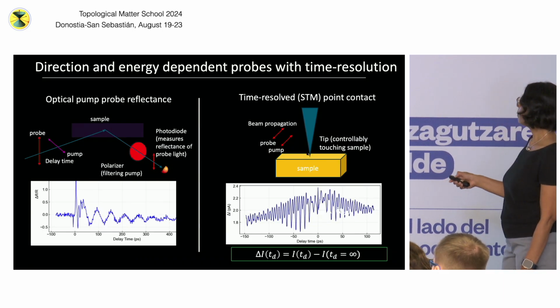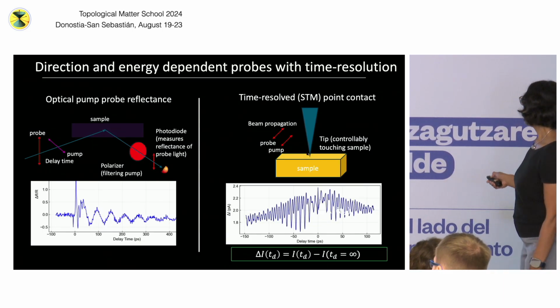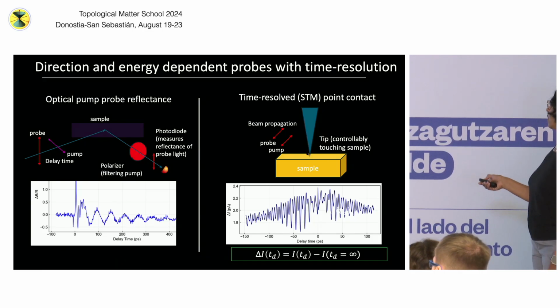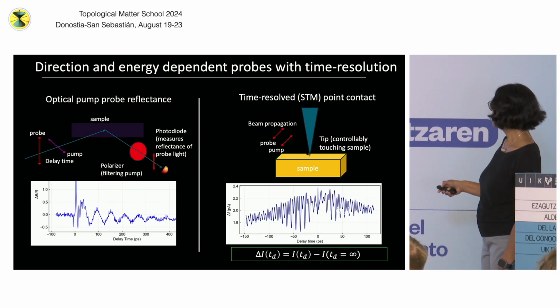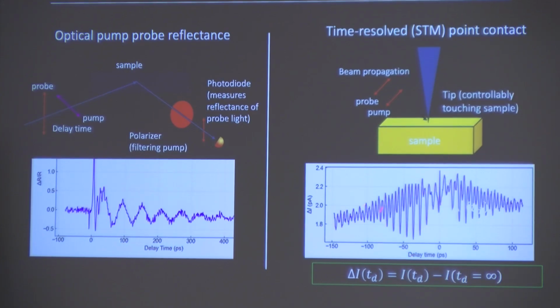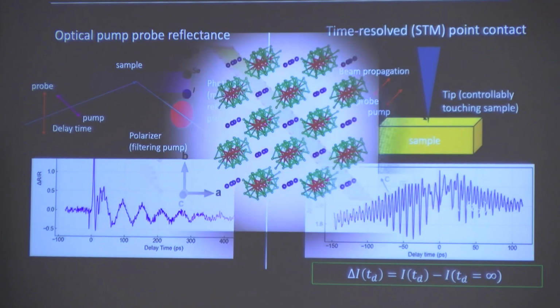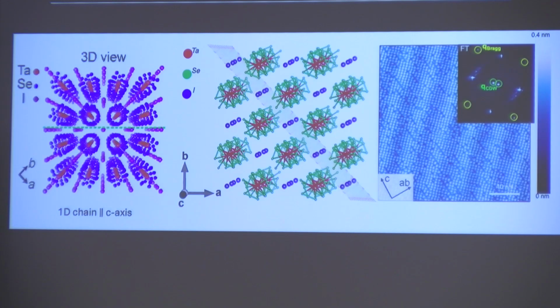This is the optical pump probe reflectivity, and this is the point contact, and I'll show you our STM data looks the same. And you can see the reflectance has oscillations on picosecond timescales. The point contact current has oscillations on picosecond timescales. And if you take a Fourier transform, you will see what I want to show you. But first, let me show you very quickly, we don't have time, this is the material. You see these stripes? That's the charge density wave. You can see it's a very long wavelength. Here are the CDW peaks, and here are the Bragg peaks.